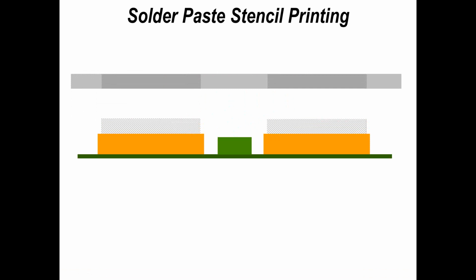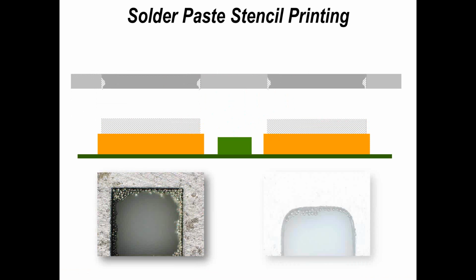So it's not just the printing process that causes the problems, it's the materials and the setup and what we add into the process. And if we don't get successful printing, then solder paste is retained within the stencil. And this can be related to the stencil, the way in which it's been fabricated, or the way it's been looked after. And here's just an example of solder paste hanging up in a stencil aperture after the printing process. Again, a common defect that many of us experience. That is the variability we're trying to monitor when we use SPI, solder paste inspection, to look at paste deposits.